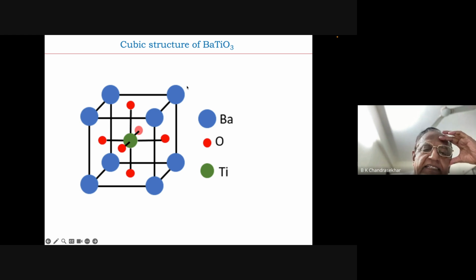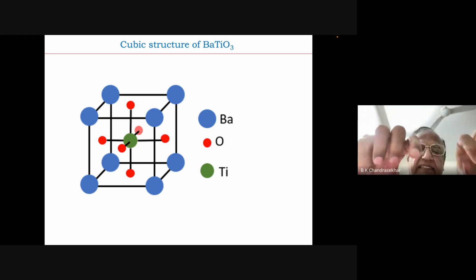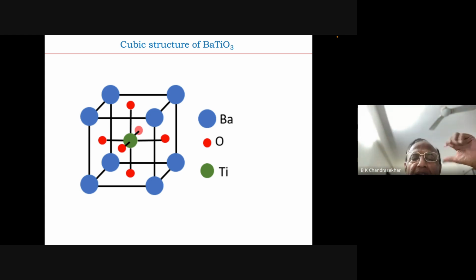So this is the structure, and this is the cubic structure above 130 degrees centigrade. Now when you bring the temperature below 130 degrees centigrade, or even at room temperature, this cubic structure, where all sides are equal, becomes tetragonal. That means the z direction is increased compared to the x direction and the y direction. This change in the phase or structure of the material makes it tetragonal.